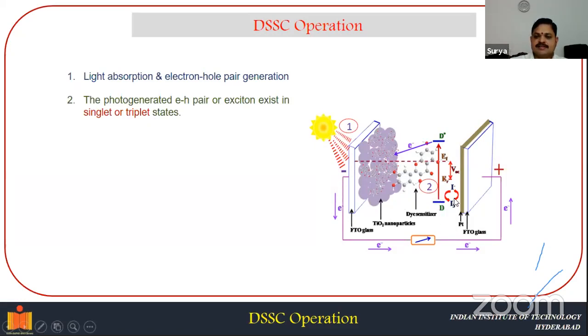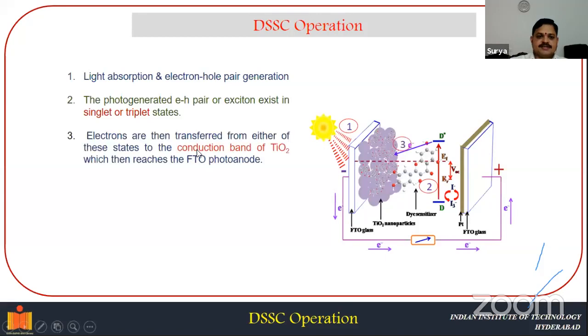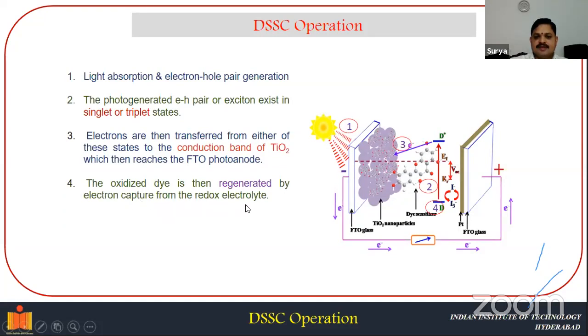Once the light falls on the solar cell, the electrons which exist in the ground state can go to the excited state. So these excitons can be in the excited state, in the singlet state or the triplet state. The electrons are then transferred from either of these states to the conduction band of titanium dioxide. The importance of this dye is that first it will absorb the sunlight from the sun, and then it will excite the exciton in the ground state to the excited state, and from there it will transfer the exciton to the conduction band of the titanium dioxide. And the oxidized dye is then regenerated by electron capture from the redox electrolyte.